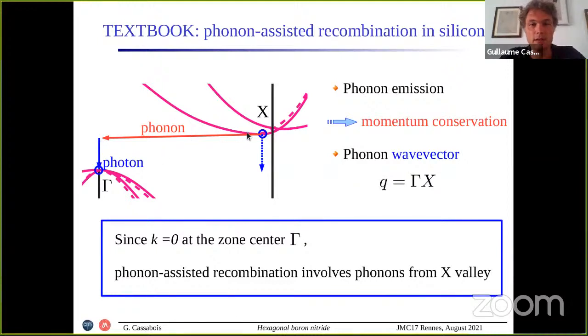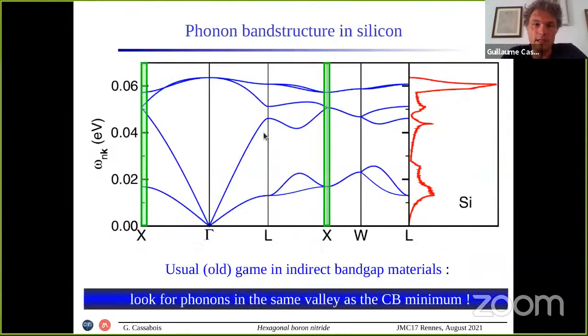Phonon-assisted emission in silicon involves a phonon whose wave vector matches the momentum difference between the zone center and the valley. What does it mean? It means that to understand the luminescence spectrum of silicon, one has to look for the phonons in the same valley as the conduction band minimum, because the valence band maximum is at the zone center. So the usual game in indirect bandgap materials is to look for phonons in the same valley as the conduction band minimum.